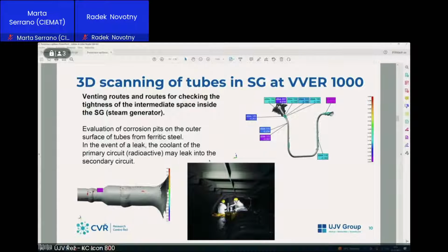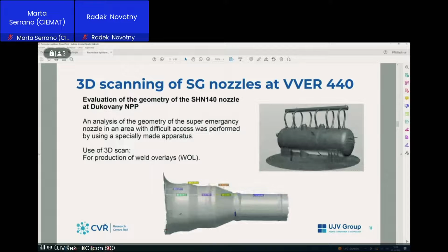The reason is corrosion pits can occur on these tubes, and in the event of a leak, coolant of the primary circuit may leak into the secondary circuit. That's why we are measuring again in these not friendly conditions: radiation, and in this case also temperature from 40 to 50 degrees centigrade.